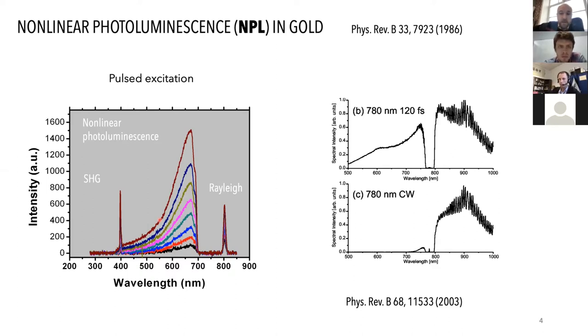Yeah, and about the second harmonic generation, as we know, there is no bulk nonlinear response, but it appears just because of the surface or edges of the gold. Absolutely. It's either mediated by the breaking of symmetry at the interface between the outside and the structure, or at one of the sharp edges of the structure. Yeah. So second harmonic and photoluminescence usually go hand in hand.